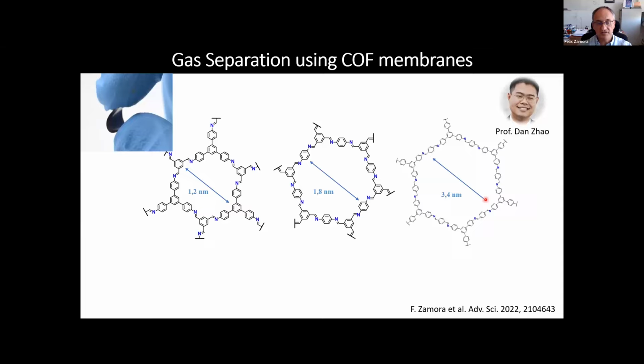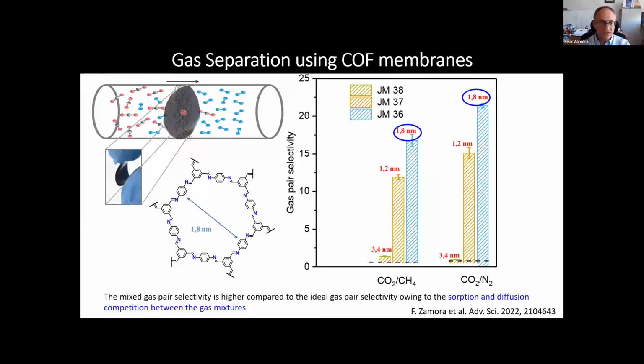The main difference between the three structures is that you modulate the cavity size, passing from 1.2 up to 3.4 nanometers. When we try to use these freestanding membranes for the gas separation of these mixtures, CO2 methane, CO2 nitrogen, we observe that we have a nice gas pair selectivity for the membrane formed with the COF showing this cavity size, 1.8 nanometer.